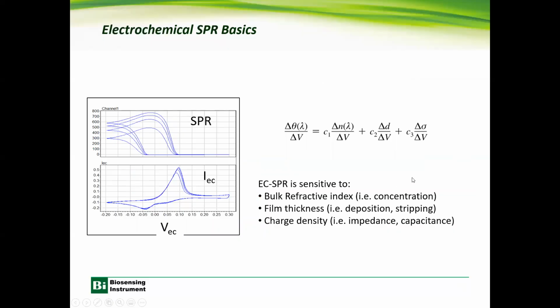So as we see, the surface plasmon resonance, the SPR response, changes as a function of voltage here. Essentially, there are two major contributions to this change. The first is the refractive index, or the dielectric property, and the second is the film thickness, and the other one is the charge density or the electronic state of the interface.